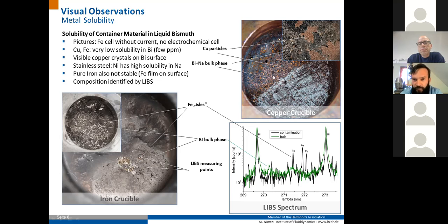And during experiments, large parts of the crucible were dissolved and somehow formed particles, which then covered the surface of the liquid electrode. Yeah, and this is something you do not want. So we then switched from copper to different other crucible materials.